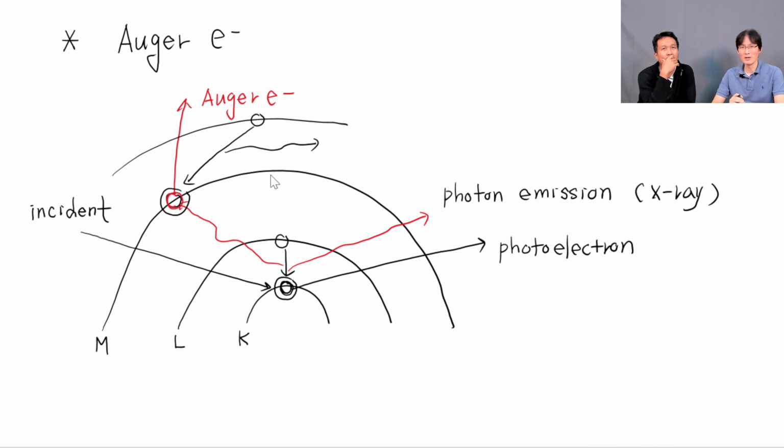The Auger electron? Really? It's a very critical aspect, in Auger electron spectroscopy. This is very useful to determine surface chemistry, and it can provide us very useful information. The travel distance of the electron is so small, within 1 to 2 nanometers, that it should be absorbed inside the lattice structure. So the experiment should include some very thin substrate, thin material. This is the Auger electron.